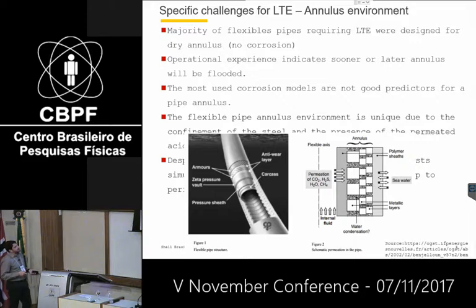Today there are no standards or procedures that you can use to simulate the Annulus environment in testing. So it's a lot of each operator doing it some way, the supplier does it in some way. And interestingly, our results are very consistent. So we could get very low corrosion rates during the confinement, but the test setup is really a difficulty. We do it differently, and it's something that we need to evaluate case by case.